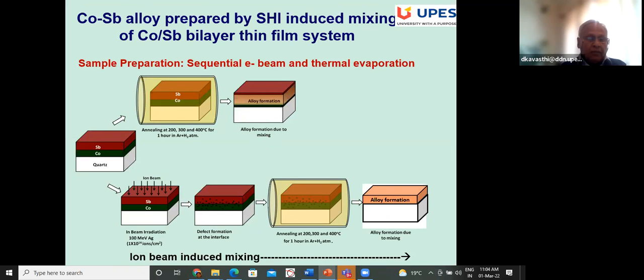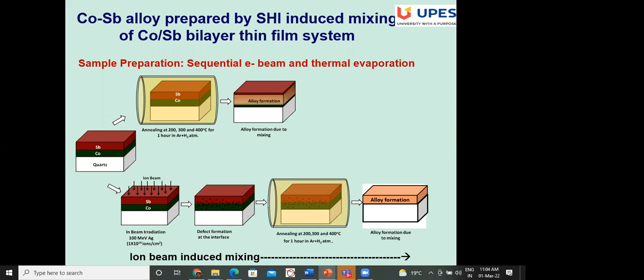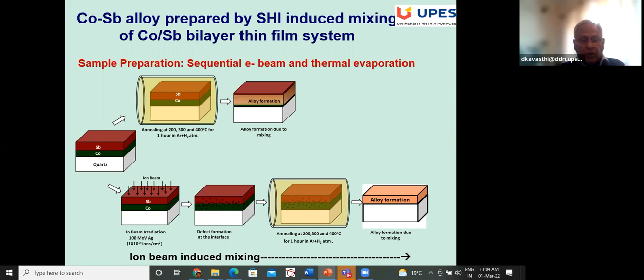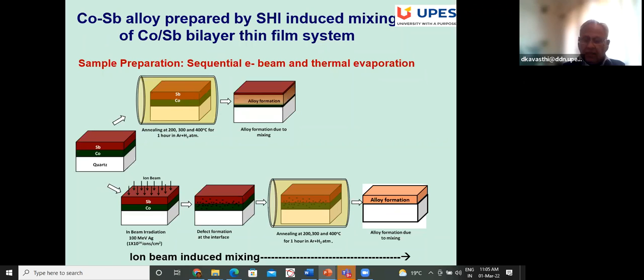Another example: antimony and cobalt on a quartz substrate. When annealed, there is some alloy formation but not complete. But if irradiated first, many defects are created, and after subsequent annealing there is complete alloy formation. This is ion beam induced mixing — you get complete alloy formation in experiments I am going to show.